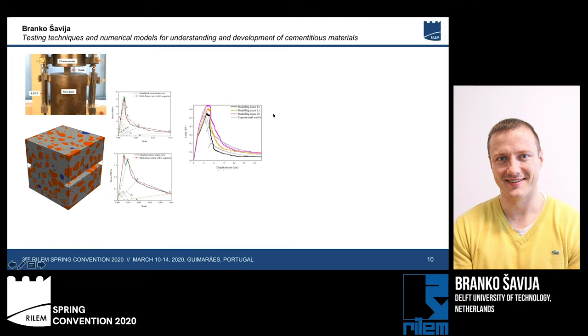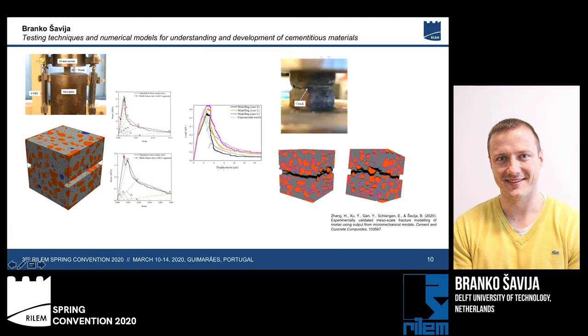Furthermore, we can compare the crack paths that we get from an experiment, which is a tortuous crack, starting from one of the notches and then connecting to the other notch, with our simulation results. And we see quite a good qualitative match.